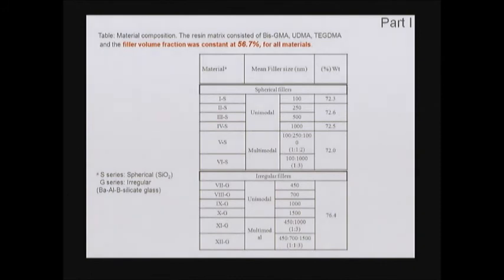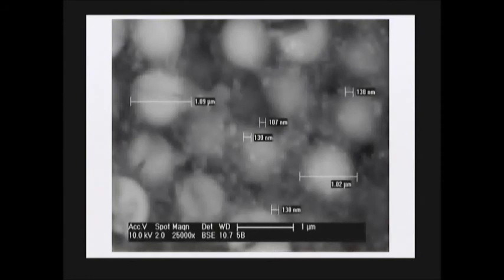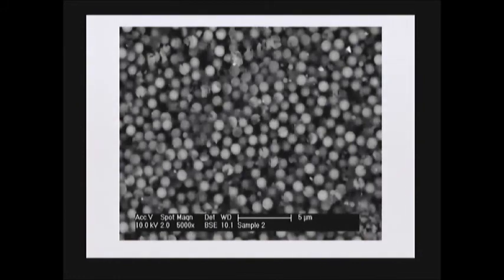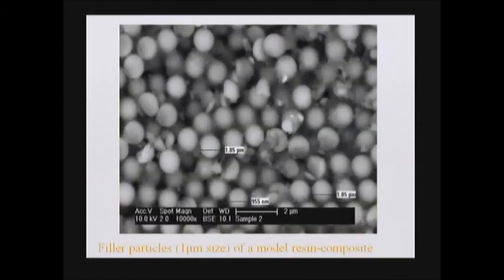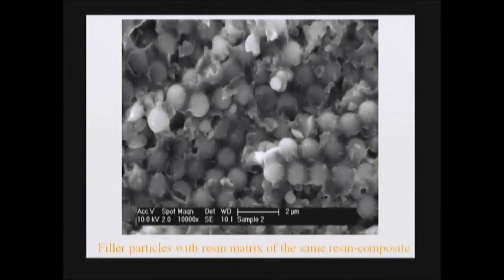This is what they look like. We took some SEM of those composites. This is one with a bimodal approach, and it has micron filler and some nanofillers at about 100 nanometers. This is one with just 1 micron. And this is a close-up with that 1 micron filler distribution. And this is the same one with the resin matrix as well in there.